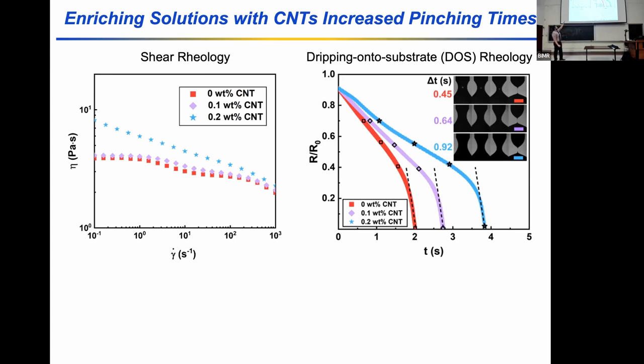And that's because we want to modify the rheological characteristics of these solutions. And the way we do that is through the addition of carbon nanotubes. And those rod-like carbon nanotubes have two effects. They create a more pronounced shear thinning behavior, which you see from the shear rheology traces on the left, where we plot the viscosity versus the shear rate. And so as you increase the carbon nanotube concentration, you increase the shear thinning response, where at high shear rates, you flow like a liquid, and at low shear rates, you act more like a solid.